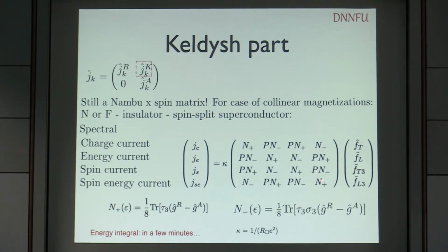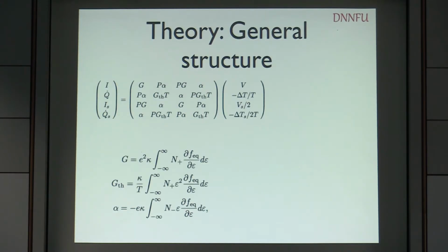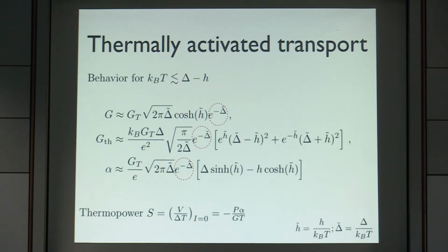The matrix is actually not 2 by 2, but 4 by 4, because you can also study spin current and spin energy currents. The general structure is like this, where you only need to calculate 3 energy integrals: one for the conductance, one for the thermal conductance, and one for the thermoelectric effects. Then you get the whole matrix by putting the polarizations and the alphas in different places. Good. This is such a simple theory.